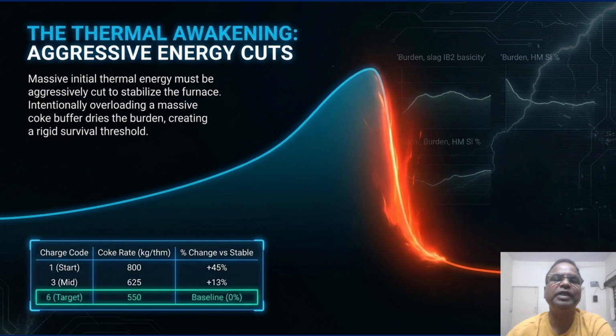We begin with a very high coke rate to secure hearth heat and dry the burden. Then we cut it aggressively to control silicon and avoid excessive fuel cost. Because if we delay in taking this prompt action, automatically our logistics will become handicapped and slowly the other running furnaces will also be paralyzed.